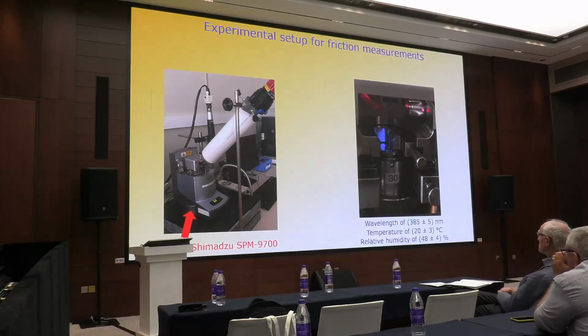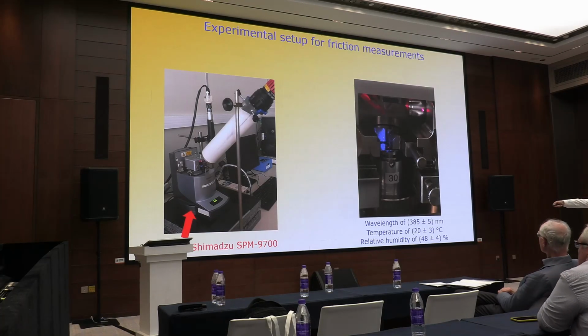Okay, let's go. We designed some experiments. We use this AFM, and we use a LED for UV to illuminate the sample. This is the sample: the silicon wafer with hydrogenated amorphous carbon, with the titanium dioxide, sorry, this titanium dioxide thin film. And we use this parameter, UV, the wavelength, temperature and relative humidity. It's not constant, as you can see it's plus or minus 4, but we perform our experiment in this range of temperature and humidity.